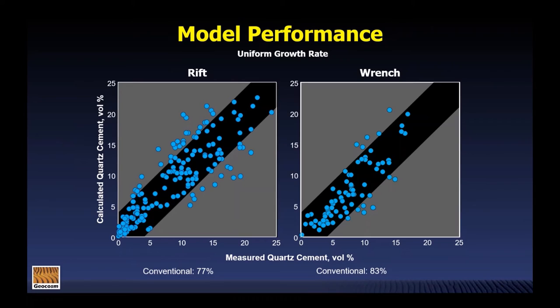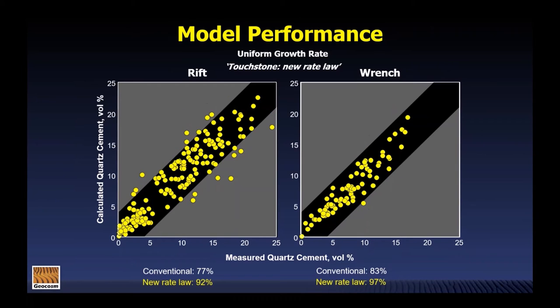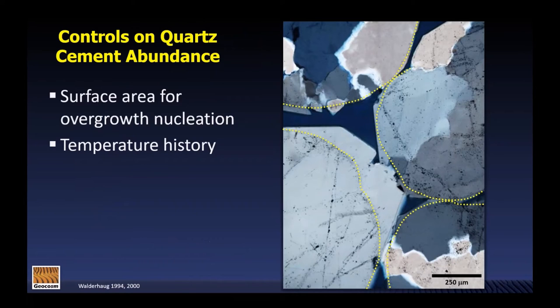So here's a model where we use a rate law that takes into account this different net rate of growth depending on the size of the nucleation domain. And I hope you can see that that tightened up these results quite a bit. And we found that in every case that we looked at, where we had a broad range of mean grain sizes, we saw a distinct measurable improvement in our model predictive accuracy. So what that means is that in addition to these important insights that Walderhaug had about the controls on quartz cementation, we can add a third factor, and that's the size of the crystal domain.